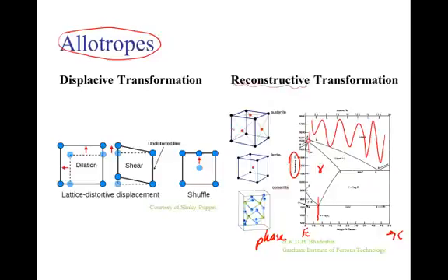And that means there's a really big difference in crystal structure between austenite and ferrite structures. You can see here with the atoms on the faces and here with the atom in the middle. So it's called reconstructive because the atoms really need to move around a lot and totally reshape the structure. That means it's going to be a slow transformation.